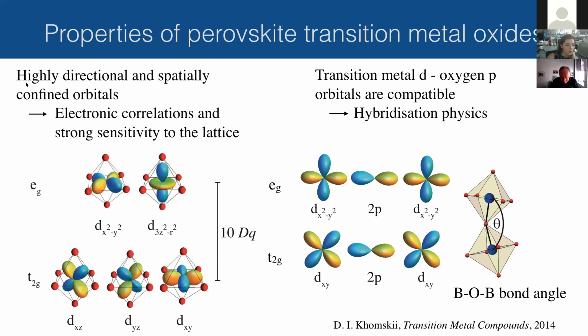What you end up with are orbitals that are highly directional. This means they are very much pointing towards one place in space, and they are very spatially confined. So they're relatively narrow. They're not particularly diffuse orbitals. So the electrons don't have so much choice over where they can exist. So there are high electronic correlations. There's a high chance of one electron interacting with another. And you have a strong sensitivity to the lattice. You can imagine if you just shift one of these oxygens a little bit, the energy of these orbitals is going to change a lot. So they will reconfigure very easily.